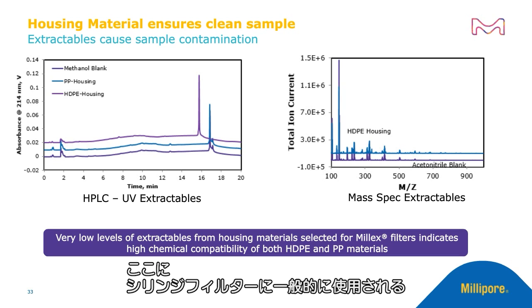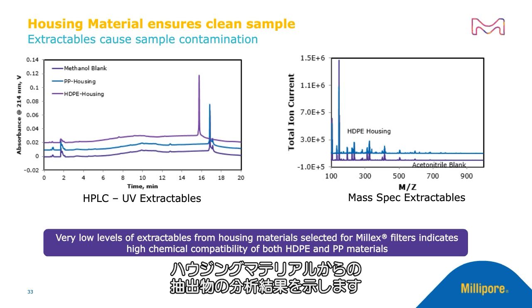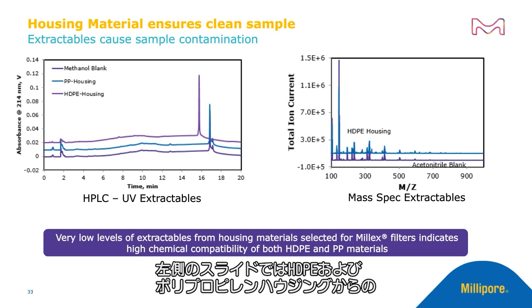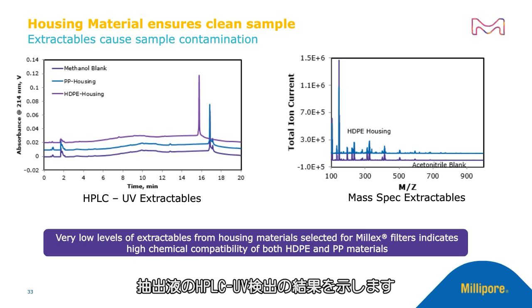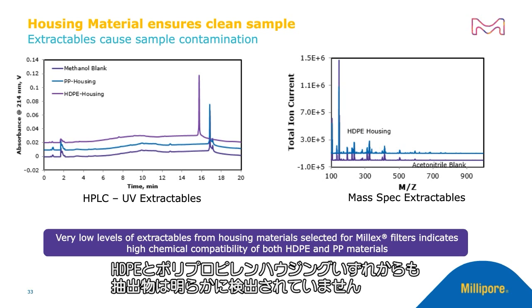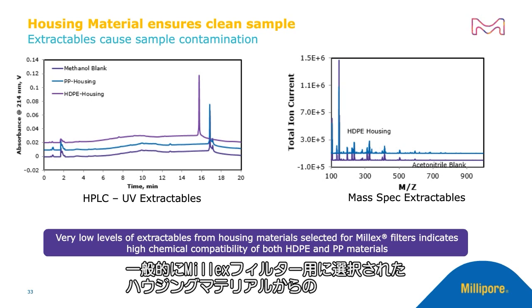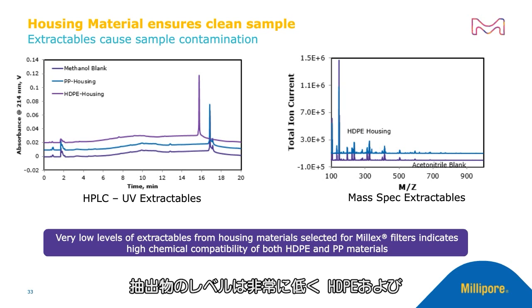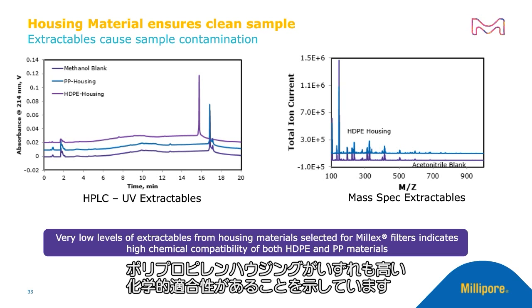Here we are showing extractable analysis from housing material that is commonly used in syringe filters. On the left-hand side, I'm showing HPLC UV extracts from an HDPE and polypropylene housing. It clearly shows that there are no extractables seen for both the HDPE as well as polypropylene housing. Generally, very low levels of extractables from housing materials selected for Millex filter indicates high chemical compatibility of both the HDPE and polypropylene materials.